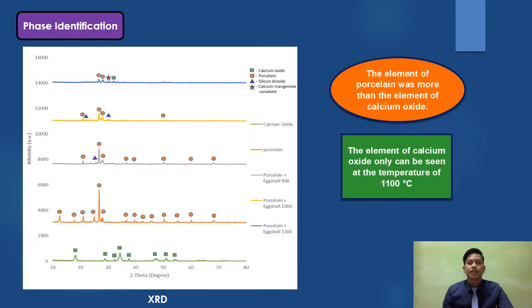For the phase identification results, there were 5 samples that had been tested for XRD analysis, which are 3 sintered samples at the temperatures of 900, 1000, and 1100 degrees Celsius, unsintered porcelain, and calcium oxide. All the results were plotted and summarized in the graph. Based on the results, we can observe that the element of porcelain was more than the element of calcium oxide for each of the sintered samples.